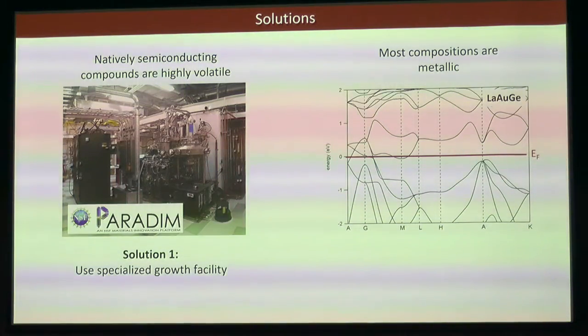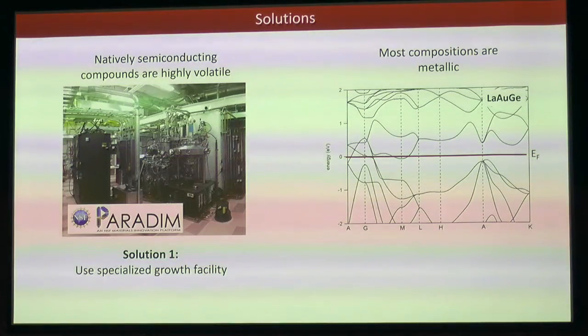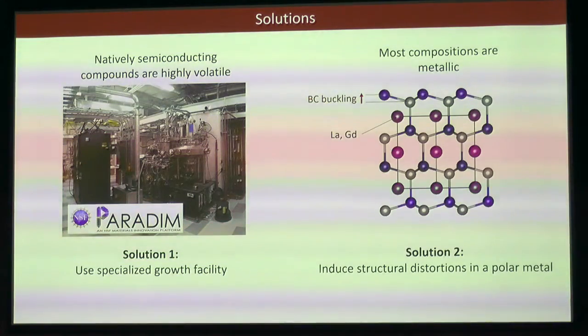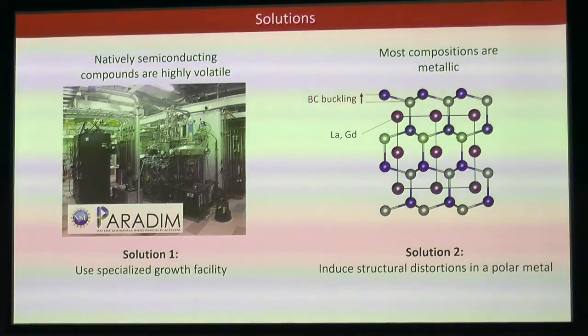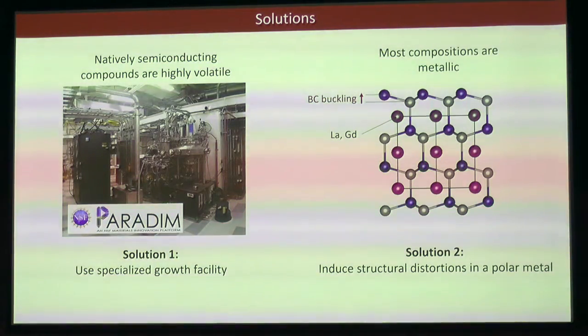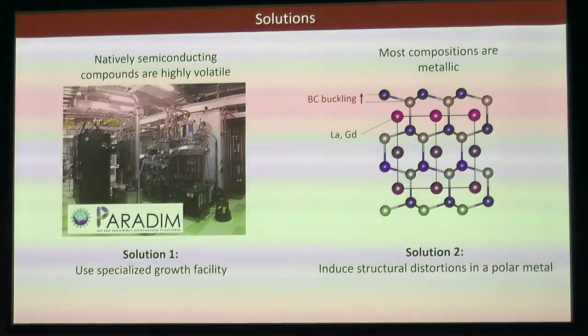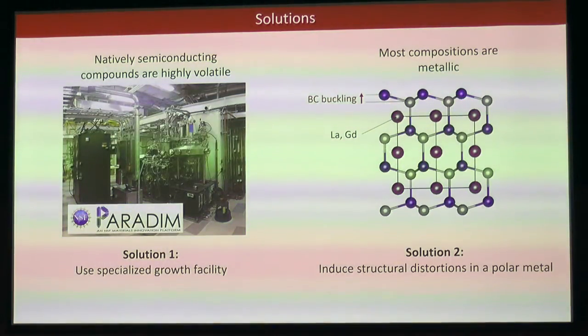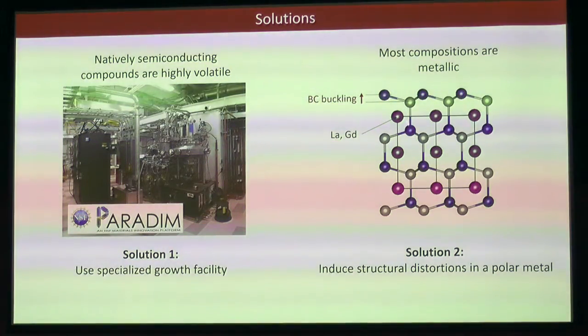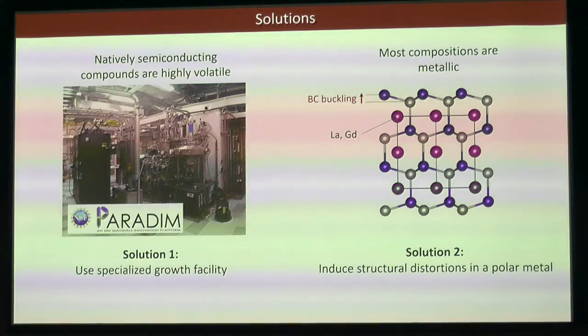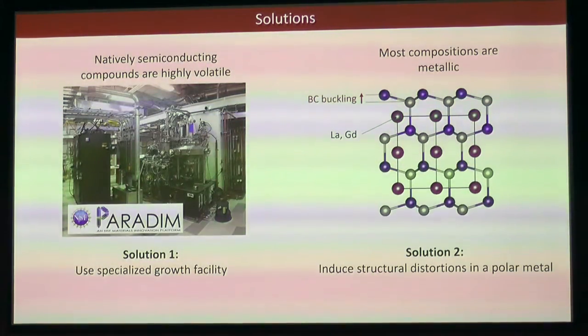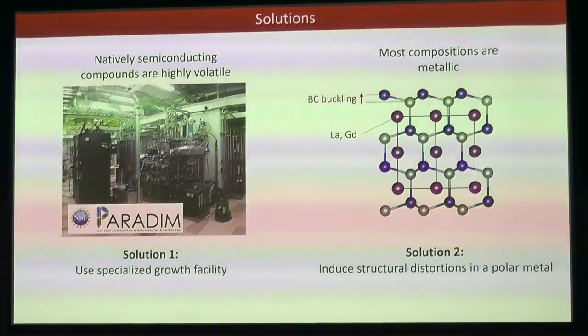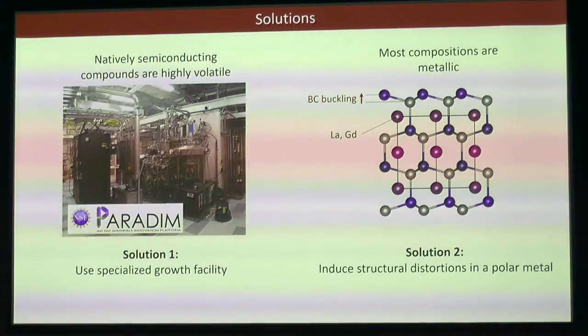Okay, so our solution to the second challenge, that most materials are metallic, is simply to start from materials that are semi-metals, with narrow band overlaps, and try to induce structural distortions and see if we can actually open up a gap. Specifically, I'll talk about alloying at this A site, trying to change the size of this A-site cation, to see if we can enhance the buckling magnitude and open gaps that way.